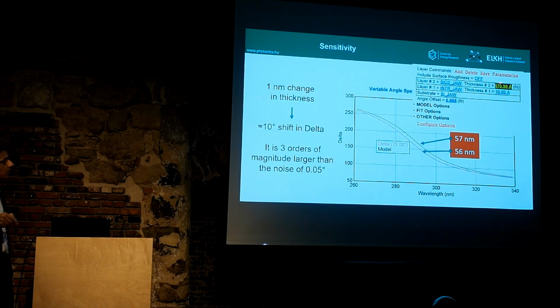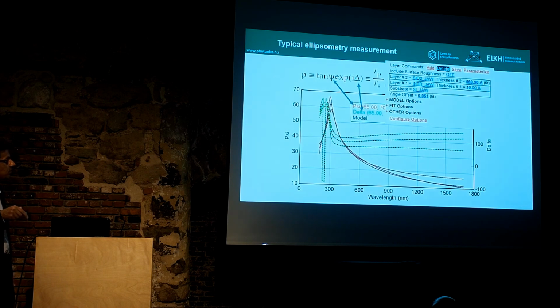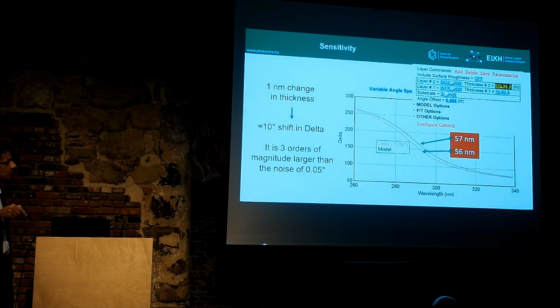But what if we change the thickness? Here, this is 56 nanometers, and we change it to 57 nanometers, so we increased it by 1 nanometer. We focus on the delta, the phase shift. The black line here is the simulation for 57 nanometers, and this purple is 56. So we change 1 nanometer in thickness, and the delta value we measure changes by approximately 10 degrees. And already from the scattering of this line, you can see that the accuracy of the measurement of this value here is 0.05.